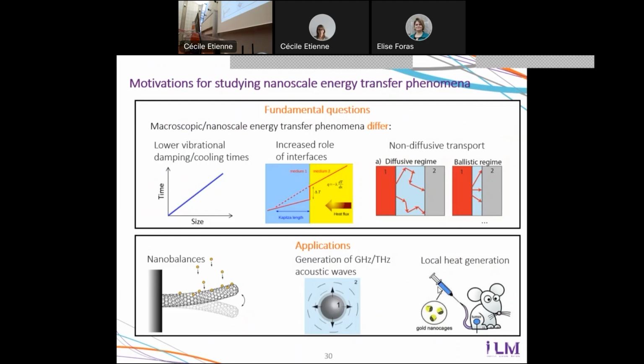Also, what is specific to the nanoscale is that interfaces play a much greater role. It's particularly the case in the context of heat transfer, because as soon as you have an interface between two different media, you will have a discontinuity of temperature, which is characterized by so-called Kapitza resistances. The idea is that an interface produces a thermal resistance opposing heat transfer. And these interfaces cannot be neglected at all when studying, for instance, the cooling dynamics of very small objects.